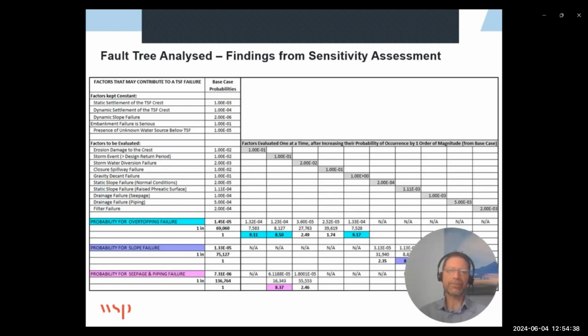If you look at the probability for slope failure, you could see that the factor identified was raised phreatic surface. That plays quite a critical role in that failure mode. And if we look at the probability for seepage and piping failure, the factor identified for the stability of the facility to be quite sensitive for was a storm event in excess of the design return period.